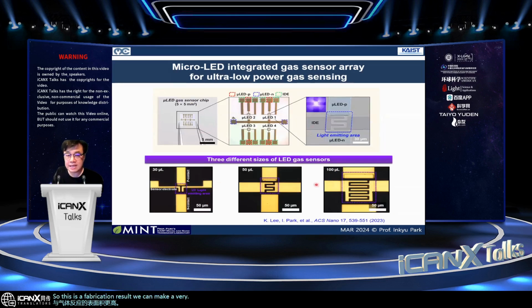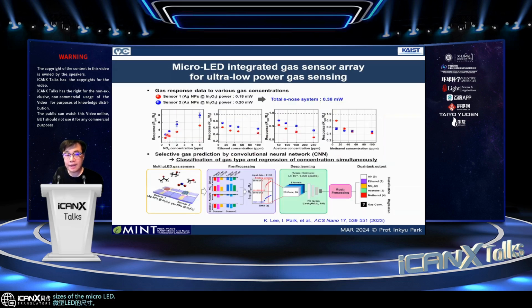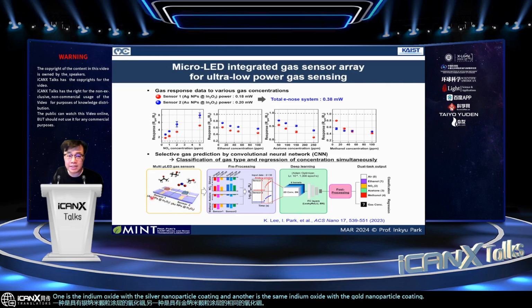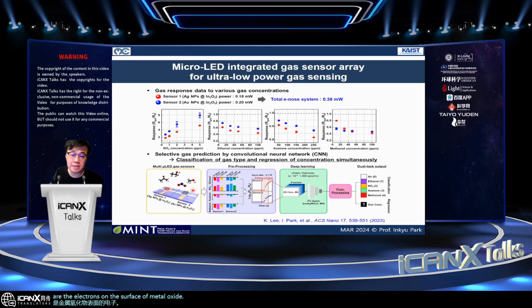We can make various sizes of the micro LED. And then use an array of two different sensors. One is the indium oxide with the silver nanoparticle coating, and another is the same indium oxide with the gold nanoparticles. By the way, the silver or gold nanoparticles are activating the surface of the metal oxide by the surface plasmon resonance effect, which makes a more active generation of hot electrons on the surface of the metal oxide. However, because they are using two different metals, they actually show quite different sensing responses.